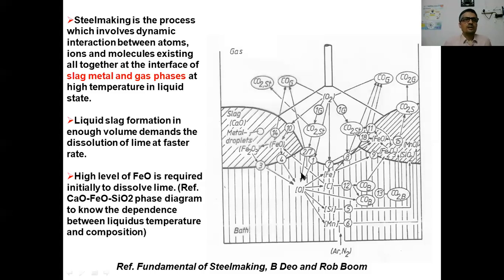Steelmaking is a process which involves dynamic interaction between atoms, ions, and molecules existing all together at the interface of the slag, metal and gas phase at high temperature. Liquid slag in enough volume is an essential requirement, and it demands the dissolution of lime at a faster rate. A high level of FeO is required initially to dissolve lime. As I already gave you the FeO-CaO phase diagram, you can understand that FeO is a requirement of the process in the initial part of the blow.